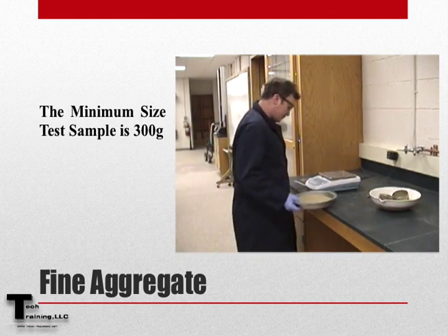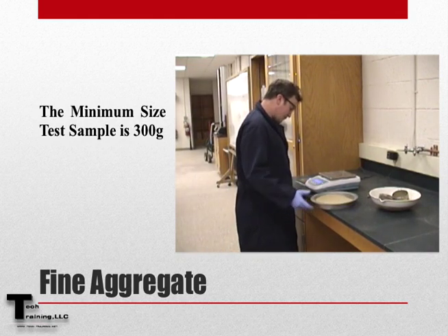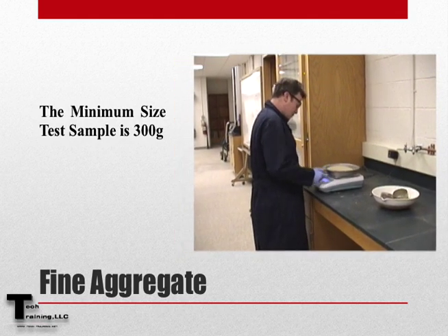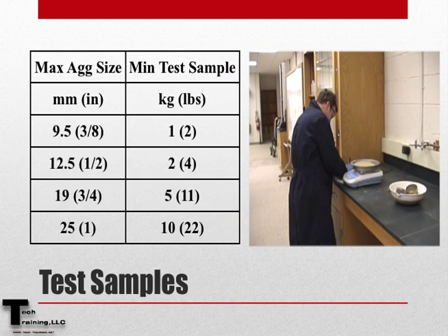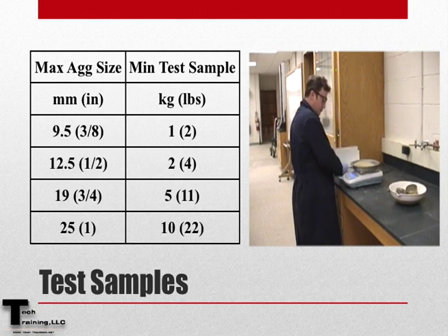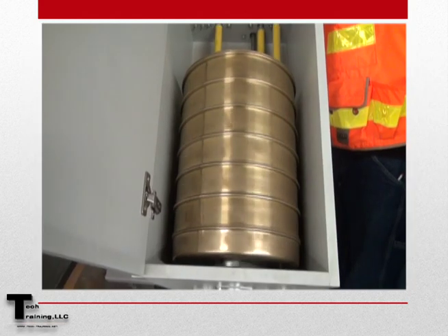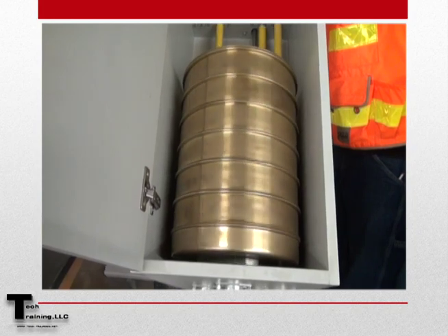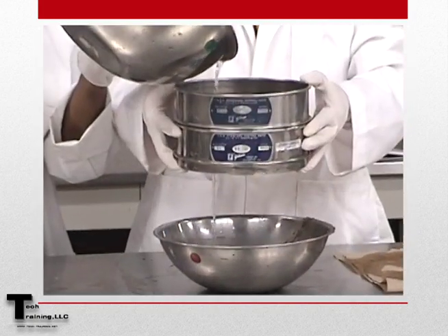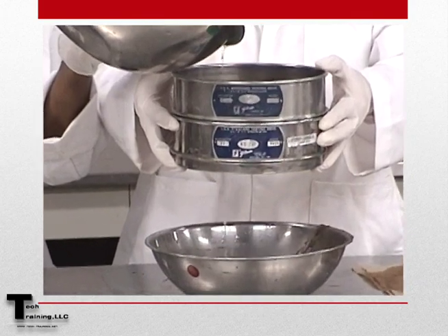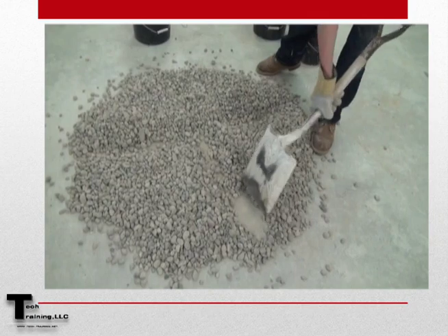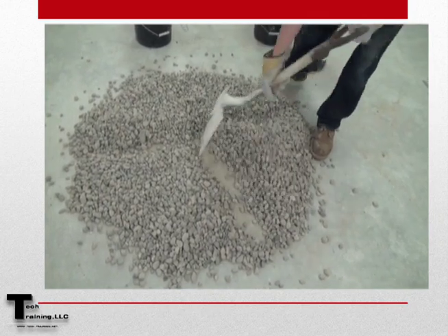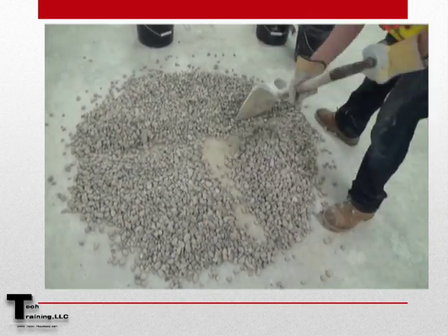Though the minimum size test sample for fine, dry aggregate is only 300 grams, the test sample size varies based upon maximum aggregate size. When sieve analysis, including the material finer than the number 200 sieve, is the only testing proposed, the sample may be reduced to testing size in the field to avoid shipping excessive amounts of materials to the laboratory.